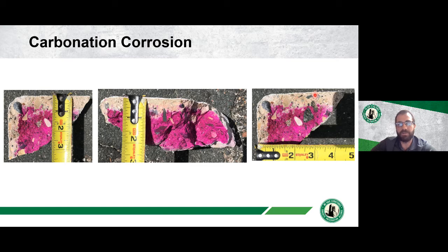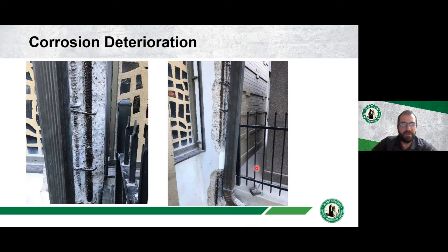Again, here about 3/4 to an inch. So we're getting about 3/4 to an inch of carbonation of the concrete. So if you look back here, that rebar is very close to the surface of that concrete. If the rebar is very close to the surface and you're getting carbonation of that first inch of concrete, it's going to cause corrosion of that steel and then spalling of the concrete.